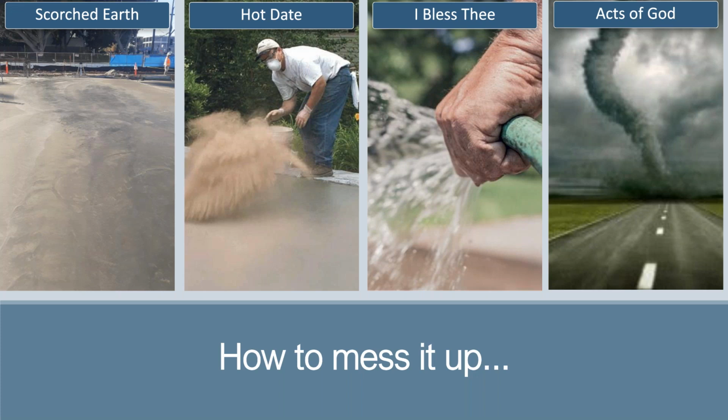Blessing the slab is another problem. You don't want to use water to facilitate finishing. That's a big no-no, and you don't think about it as being a problem, but let me help you. If I start with a 0.45 water cement ratio and I add 2 tablespoons of water during the troweling operation of finishing, I can increase that surface paste to a 0.8. That gives me a hot spot where any flooring that goes down over that blessed section is going to fail.